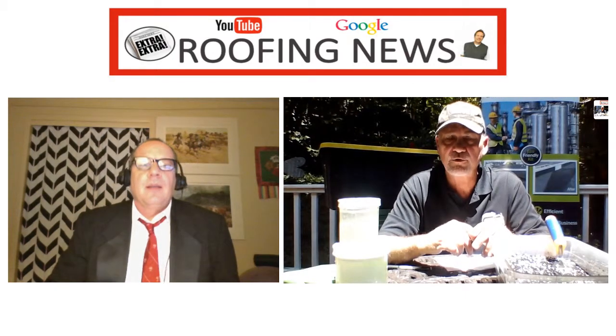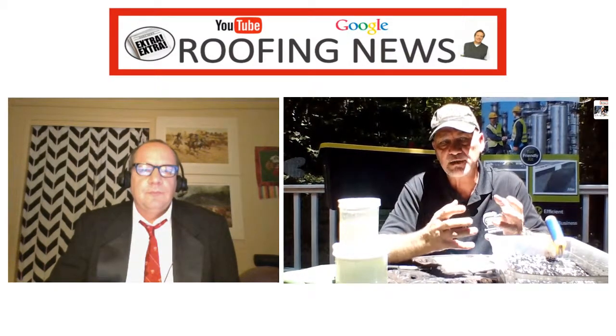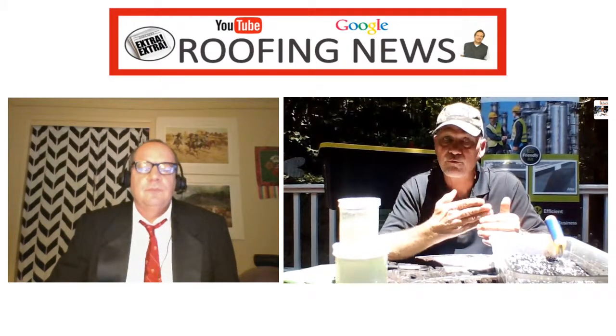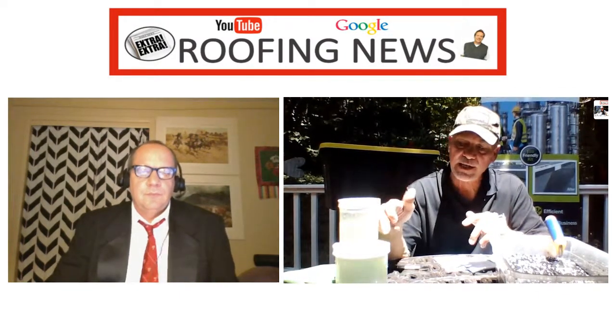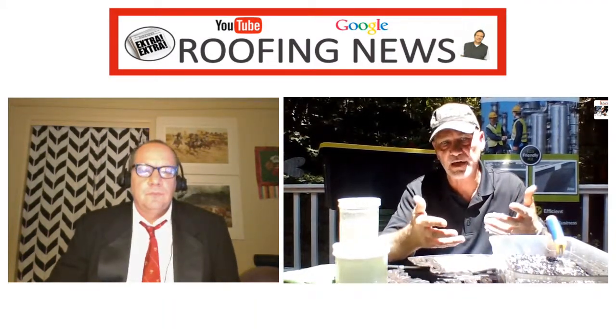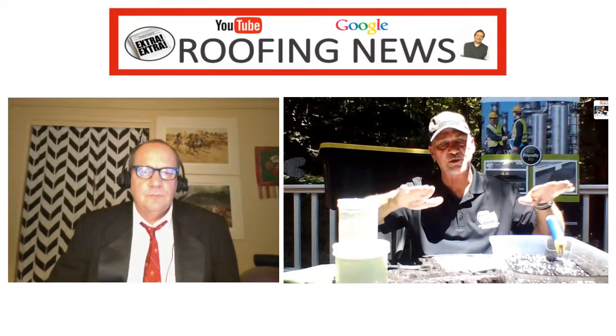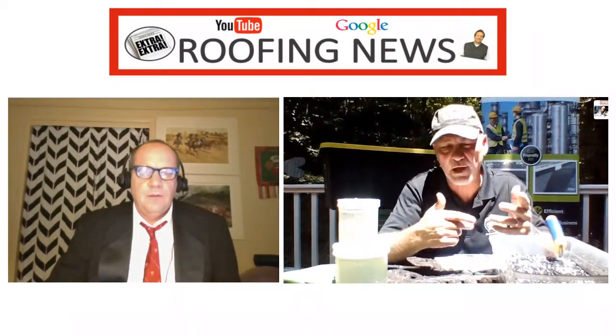And then do you apply the primer? Does that go into the area where you fill it, or is the primer just for the mix? No, the primer will go into the area you've cleaned, just like paint. The reason we do that is we really try to stick to good roofing practice, and we want a good uniform bond in your repair area, even though it's the same product. In reality, since these granules don't absorb the adhesive, everything filters down or almost self-primes with the excess adhesive, if that makes sense. But the primer gives us a good uniform bond, and it's real important around the edges of where you're putting it, so you get a good bite to that existing roof. So it's belts and suspenders for the most part.